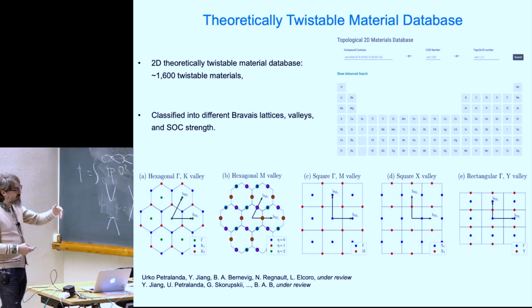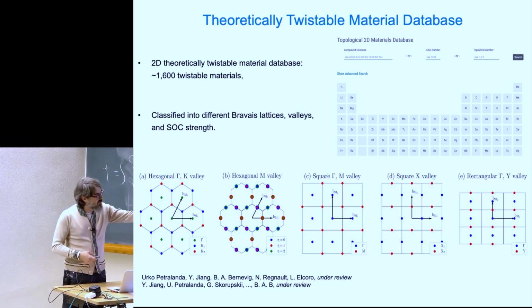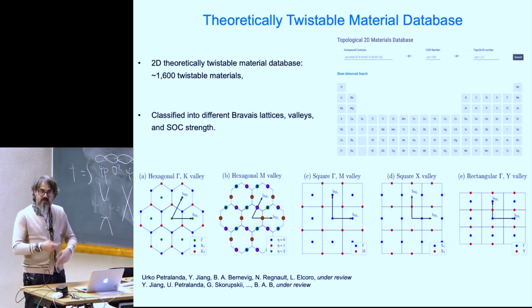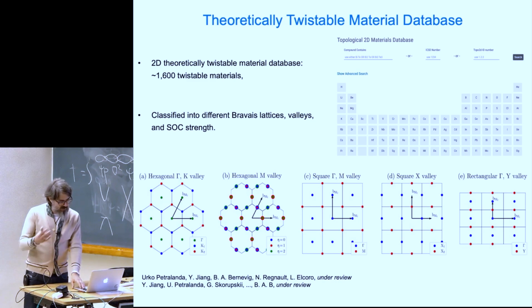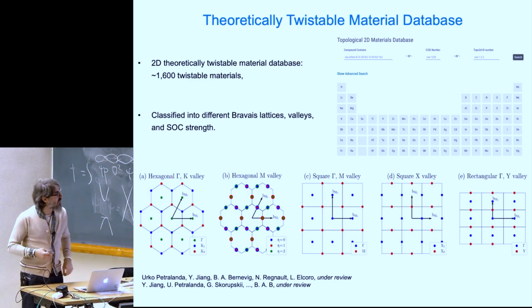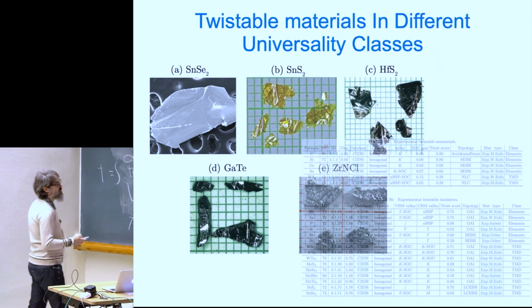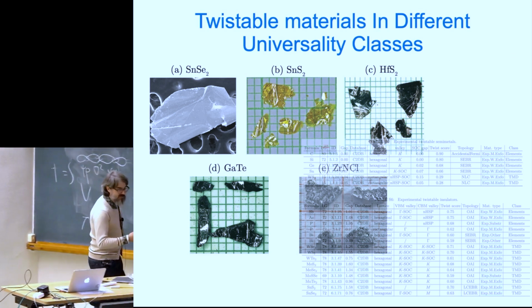At the K point, but there's also the M point, there's also the gamma point, etc. There are different lattices, with or without spin-orbit coupling, so you can make about 37 classes of this. Now, to show you that this is not just a classification, these are crystals grown by Claudia Felser and Leslie